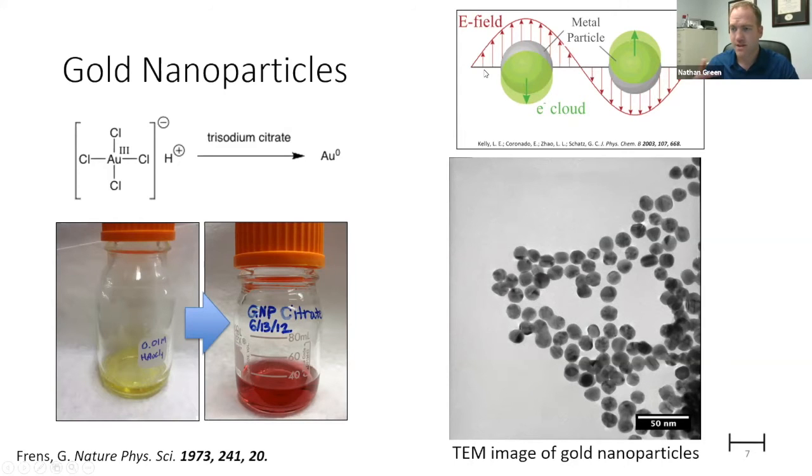So a wavelength of light is really two orthogonal fields of electromagnetic radiation. Well, the electric part of this, as the wavelength goes over top of the particle, would push that electron cloud down, and as the wavelength comes underneath the particle, would push the electron cloud up. And so that cloud goes down and up and down and up and down and up, and it resonates back and forth. Well, in chemistry terms, when we talk about something resonating or a dipole resonating, that's really absorbing light.